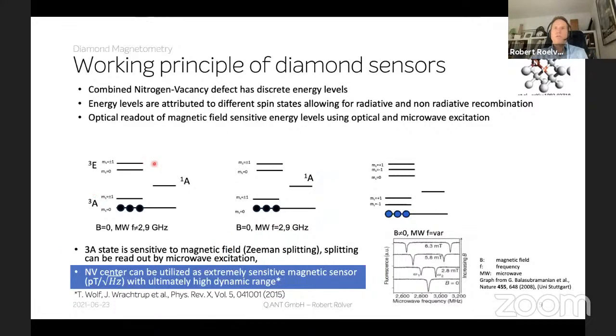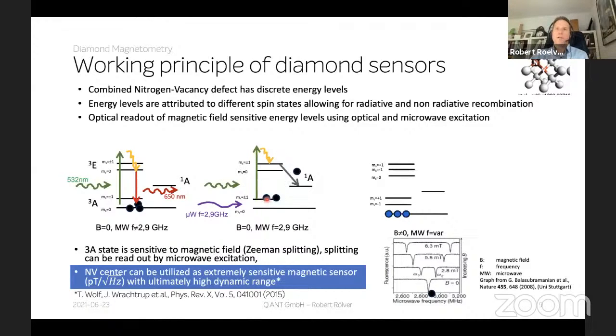Before, just a brief introduction of the working principle, already done in the first talk today. So we have this NV center, nitrogen in the vacancy in the diamond lattice, forming a defect within the band gap of the diamond, having these discrete energy levels, and you can probe the magnetic sensitive position of the energy levels just by shining light onto this defect, and you have a red fluorescence. If you have an additional microwave field, then due to spin conserving, the electrons are excited to the ms plus minus 1 level here on the top of the energy scheme.